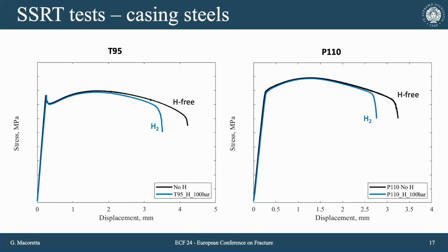If we look at the results of the slow strain rate tensile test, in this case it's even more evident because we have a reduced scatter of the data. The effect of hydrogen takes place only in the plastic portion of the curve. The elastic part of the curve is identical, and so is the yield phase, even in a material like the T95 that has a discontinuous yielding phenomenon. The two curves start to differ mostly after necking, just a bit before necking for T95, and only after necking for P110.